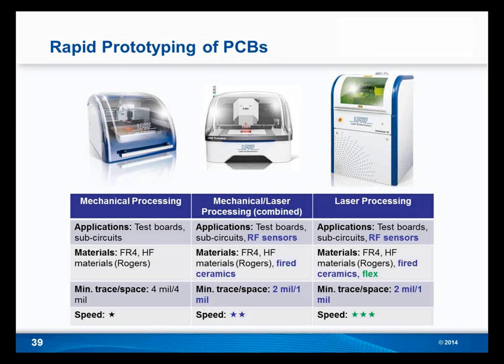And when you take that one step further, you get to laser processing. We have a couple of different units, an IR laser and a UV laser, designed to remove the surface metallization extremely fast, on the range of 4 or 5 times faster than mechanical, which gives you cleaner edges and less effect on the substrate for a lot of materials, and opens up the door to work on materials like fired ceramics, where mechanical milling would not allow for that to be processed. And even flex applications; we're seeing advances and additional materials being processed with the lasers every day. With that, you can go very, very small, with a 15, 20, or 25 micron beam width, and the speed is incredibly fast, as I mentioned before. So that's kind of a brief history of the past and what we've planned for the future, the tools that we have available. Gotcha.